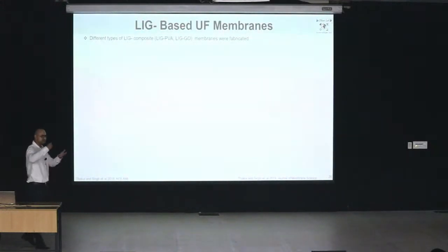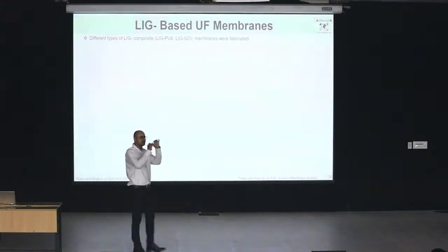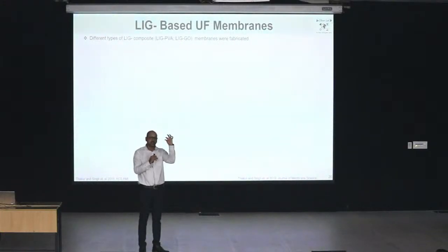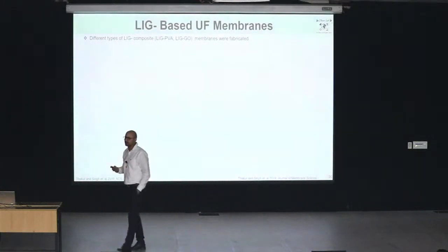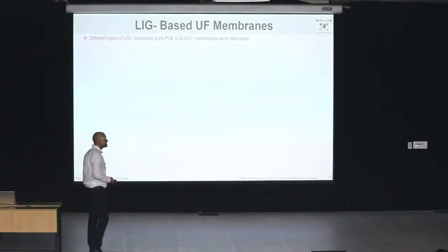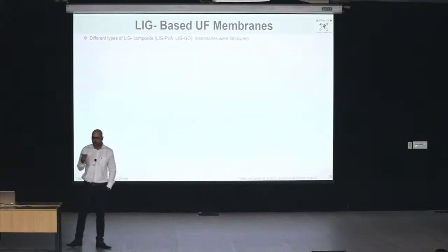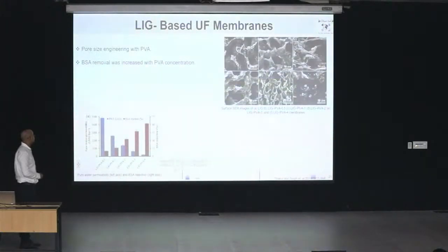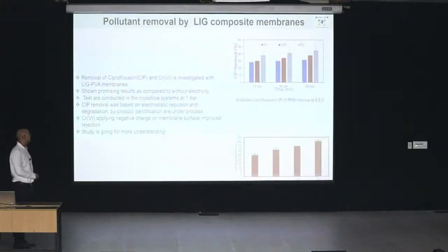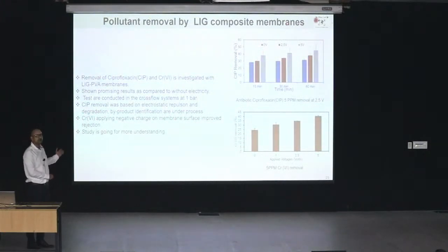When it comes to membranes, if you are not aware, let me explain: only the top few micrometers are the active layer. When we burn these surfaces with the laser, it destroys the top layer. For example, if you are using an ultrafiltration membrane whose pore size is a few hundred nanometers, when we burn that surface, it converts into a filter. So to convert it into a membrane, we have to do a post modification. We have done several post modifications, and by that we have come up with different kinds of membranes such as LIG PVA and LIG GO, and both have demonstrated very good separation processes along with antibiofouling properties.